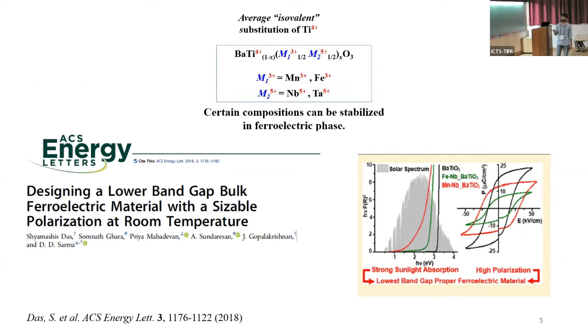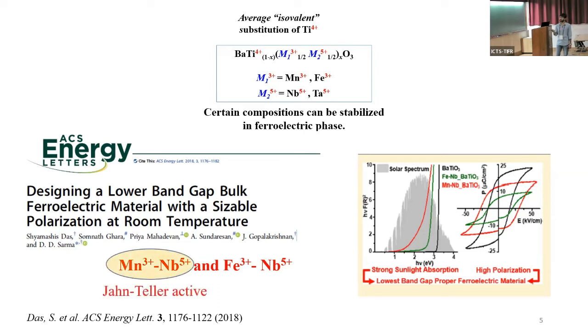From our group designed a lowest band gap ferroelectric material by using a manganese and niobium pair and contrasted it with an iron and niobium pair. Now one can see from the following data that the band gap for manganese and niobium doped barium titanate is reduced to a very considerable extent as compared to the iron niobium pair, which is around 2.5. Also, this strategy led to retention of ferroelectric polarization to largely 70% of the inherent BTO, barium titanate, I should call it. And the reason for such usefulness of the manganese 3+ and niobium 5+ pair as compared to the iron and niobium pair was attributed to the Jahn-Teller activeness of the manganese 3+ ion.